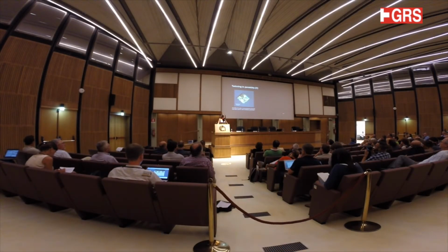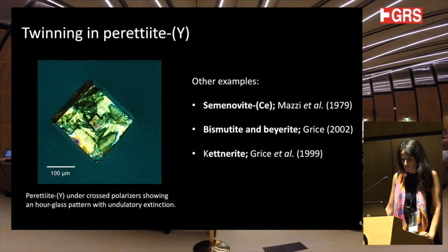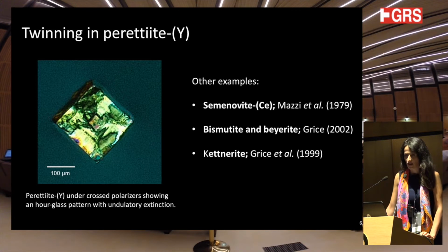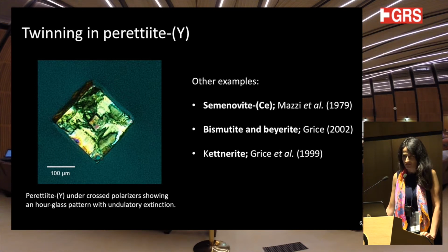And now we look at a crystal cross-section. This is a cross-section of 010. And what we notice is that the crystals are mimicking tetragonal symmetry. But under crossed polarizers, they show this hourglass pattern with undulatory extinction. That suggests that there is a problem with twinning, so the crystals are intimately twinned. Therefore, we interpreted this as a 90 degrees rotational twinning along the short axis. And so we could solve the structure as a 50-50 pseudo-merohedral orthorhombic twin.